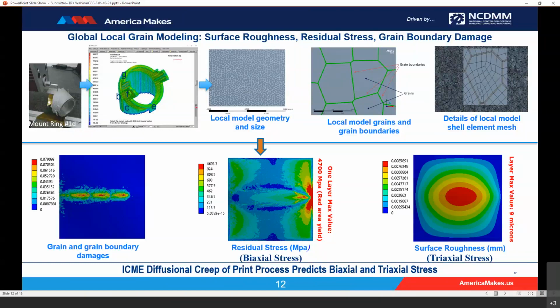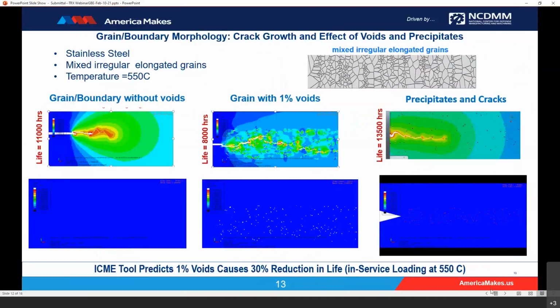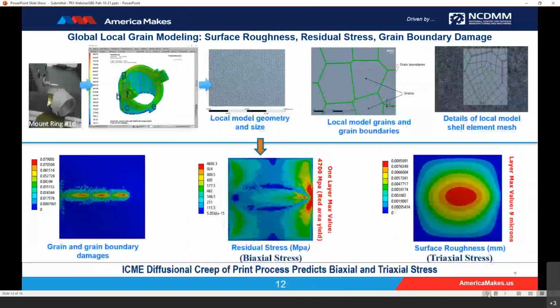As you can see on the image on the far left, bottom left, we're predicting from this global-local analysis grain and grain boundary damage. The image in the center, again looking at that grain, can predict residual stress, biaxial stress. And finally, for triaxial stresses, we can then predict surface roughness. Ultimately, ICME diffusional creep supports the print process.